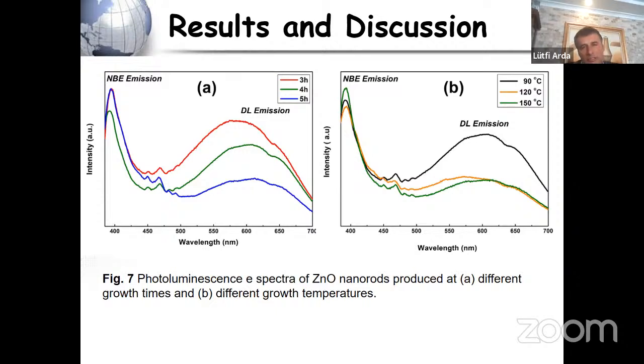When we look at this figure, there are two dominant emissions: a sharp ultraviolet emission peak on the left side, and a broad visible emission band on the right side. This corresponds to typical n-type zinc oxide semiconductor. Ultraviolet emission is responsible for the crystallization quality and defect quantity of zinc oxide, and the visible region emission, the deep level emission, is also in charge of originating from defects.